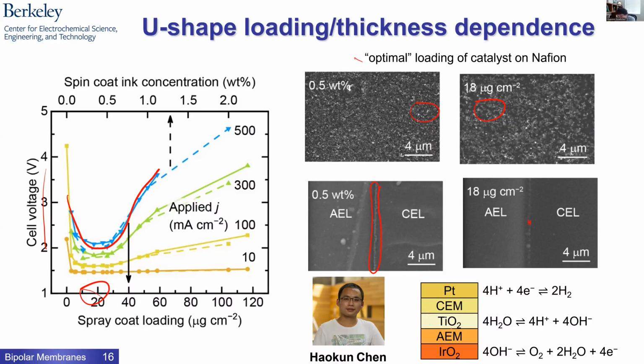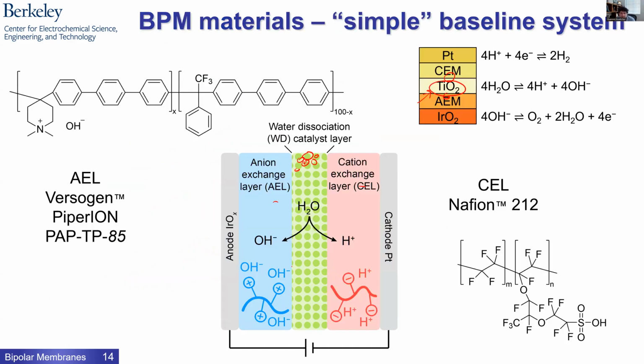I said, Haokun, this is actually really obvious because you have all these particles here, right? And if I make H plus and OH minus in the middle of this catalytic layer, if it's really thick, it has to move through a very thick catalytic layer. And these polymers are made to conduct hydroxides, but these are just metal oxides. They're probably not very good proton and hydroxide conductors. So it probably will have some ohmic loss here. So I'll call this an ohmic loss, and the junction here associated with that. So that was the hypothesis.